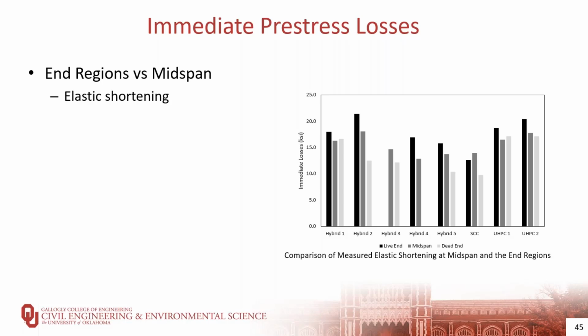The values of the elastic shortening correspond to the high compressive stress and strain at the UHPC end regions and the lower compressive stress and strain at the SCC end regions, which is related to the location of the strain gauge relative to the transfer length.